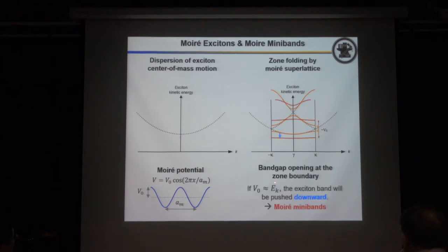But if the potential modulation is large or comparable to the kinetic energy, the dispersion will become very flat, and it will be pushed downward to form this kind of miniband. That means if you can control the potential modulation, you can modulate the exciton energy like this. But it is not easy to control the amplitude of potential modulation. But you can change the periodicity. Now, if you change the periodicity, actually you get the same behavior, because a smaller periodicity means that you have larger kinetic energy at the zone edge. That means that the same potential modulation will be small compared to the kinetic energy.